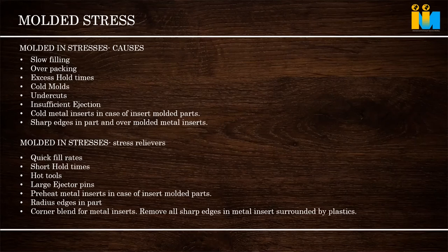What happens? This area will fill properly, but just to compromise for this area, we are compromising all the other areas, and all the others will be overpacked. Okay, we are supplying extra food for them. It will be overpacked, especially amorphous. This is a danger condition. Polycarbonate, polystyrene, PPO, Noryl, ABS, most amorphous plastics, be very careful with this.